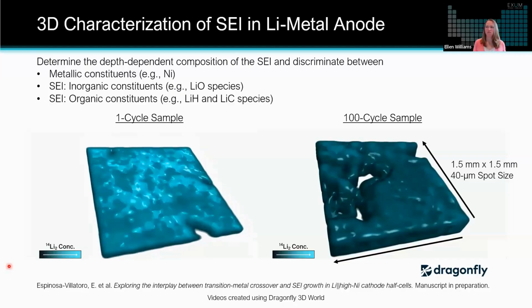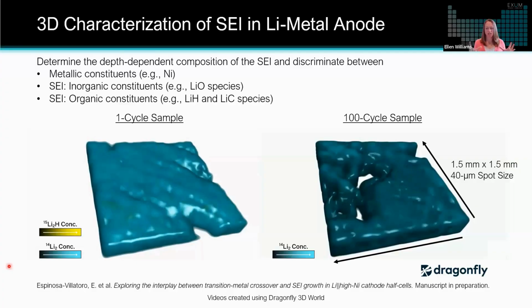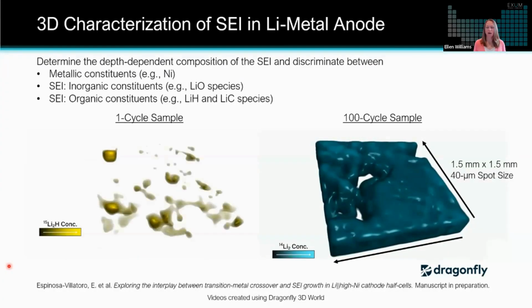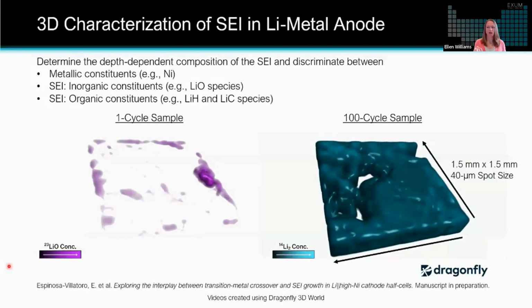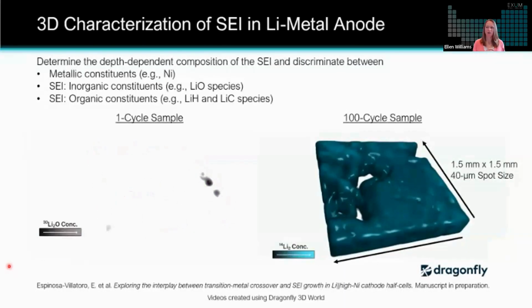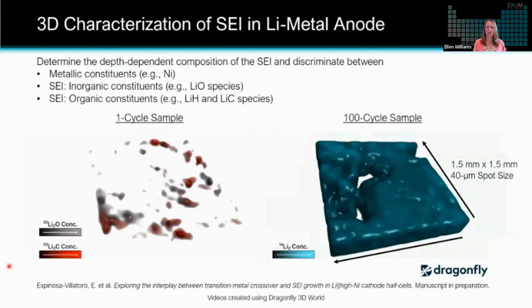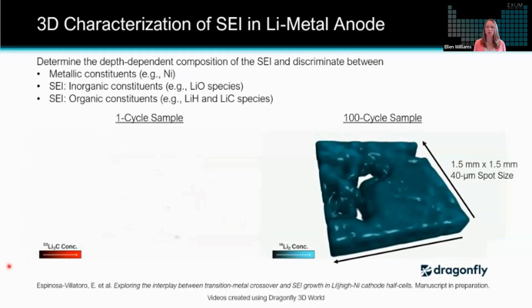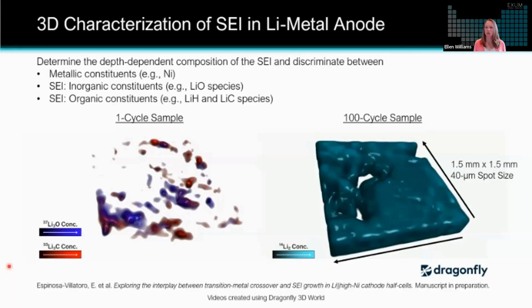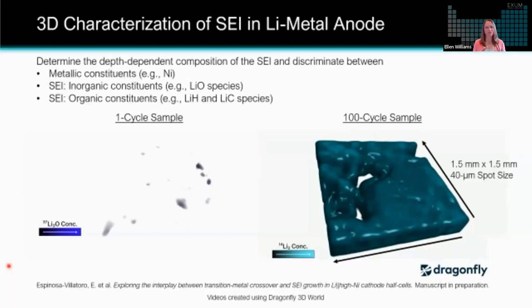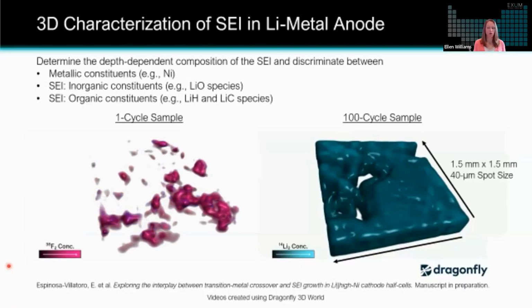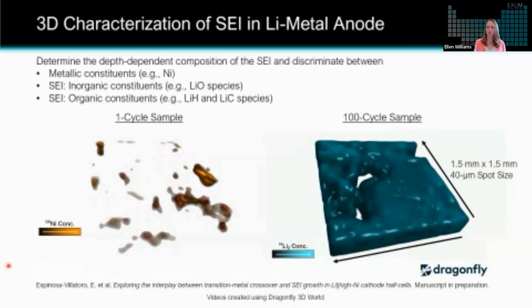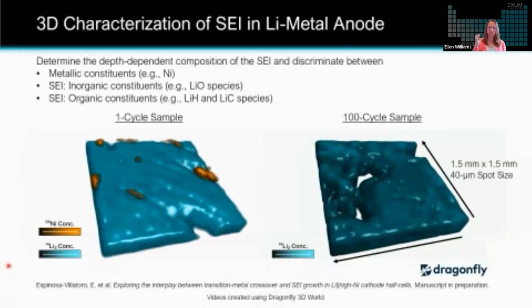So first I'm going to play the video from the one cycle sample. So you can see, this is mostly a lithium metal anode. We see lithium combined with hydrogen populating in one area, the lithium combined with oxygen in another area. But overall, we don't see a super dense SEI formed quite yet after this one cycle. So again, noticing how the different constituents are distributed, as well as fluorine, which you see in pink, which was also identified here. I should also point out that these were more on the surface. These analyses were done with 5 layers on each of these samples.